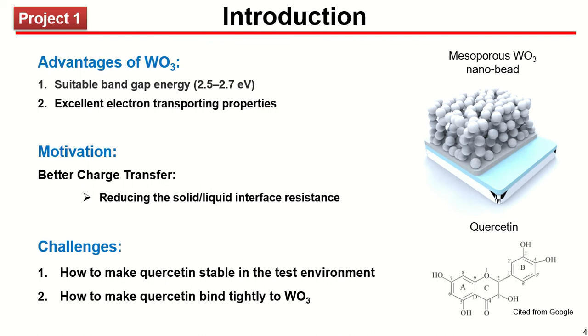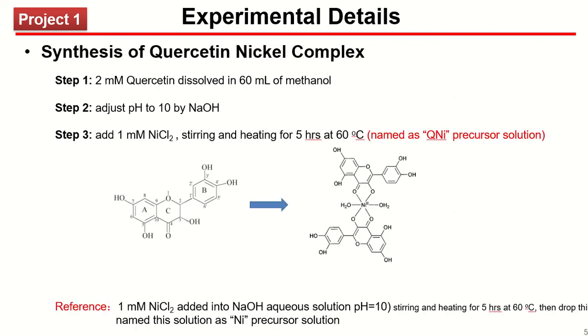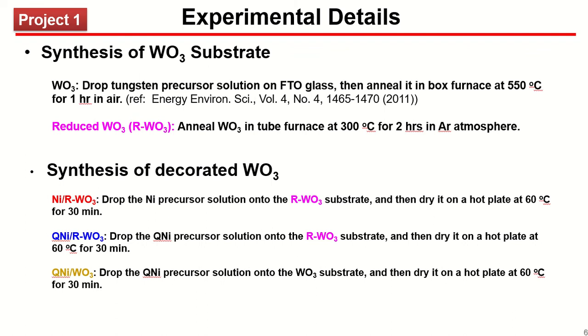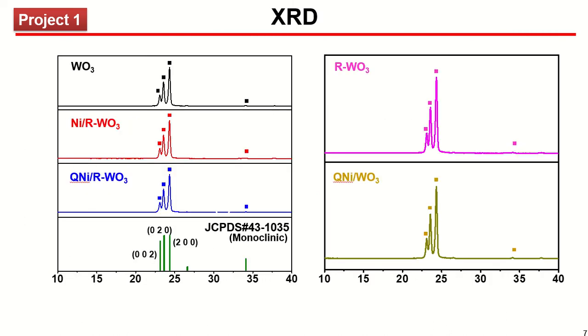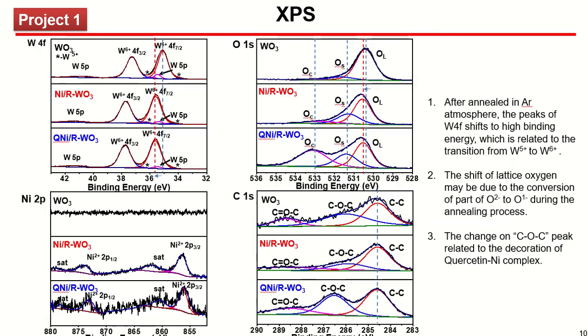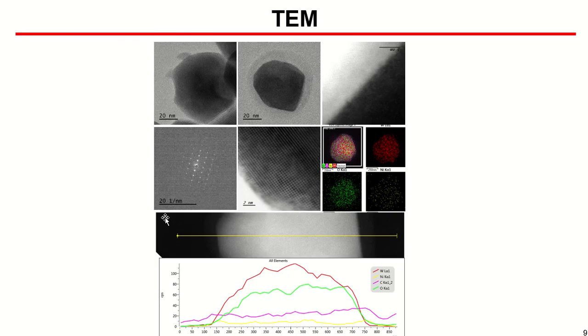Now we choose quercetin. In our work, we try to transfer the quercetin into a quercetin and metal complex. During our experiment, we choose nickel as the metal. Based on the following protocols, we decorated the quercetin nickel complex on the surface of tungsten oxide photoanode. As the characterization results show, we successfully decorated the quercetin nickel complex on the surface of tungsten oxide nanoparticles.